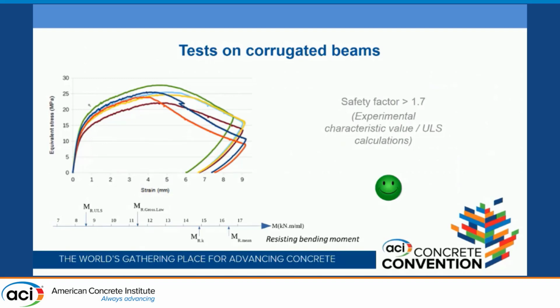This test confirmed that the use of constitutive laws to verify the cross-section applies well to UHPC with compression values of 130 MPa.